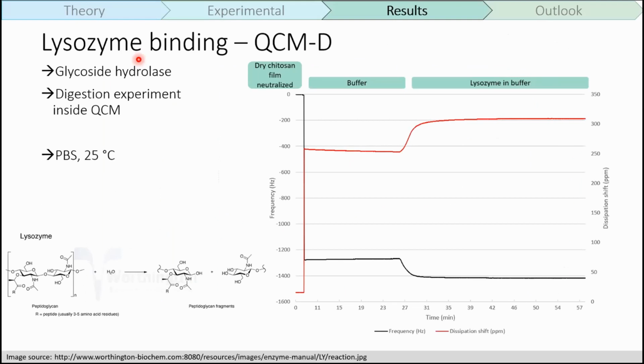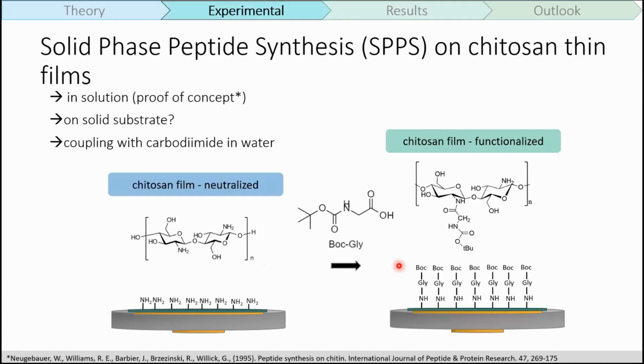Moving on to functionalization, we wanted to try if our film could be digested by lysozyme, an enzyme. By introducing our film to the lysozyme buffer solution, we see the frequency shifted to lower frequencies, meaning that some mass was deposited on our surface rather than dissolving or digesting it. So in this case, the lysozyme didn't digest our surface, it rather bound to the surface somehow. But this is quite a recent experiment, and some more characterization methods and analytics had to be done to confirm that.